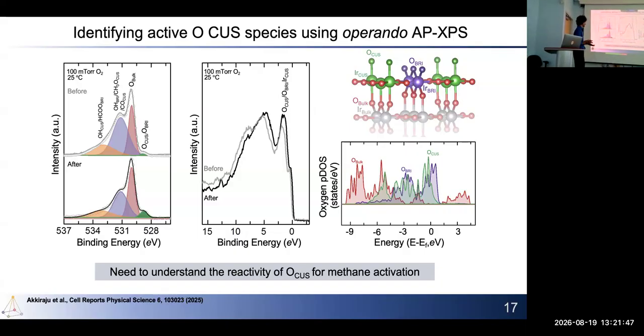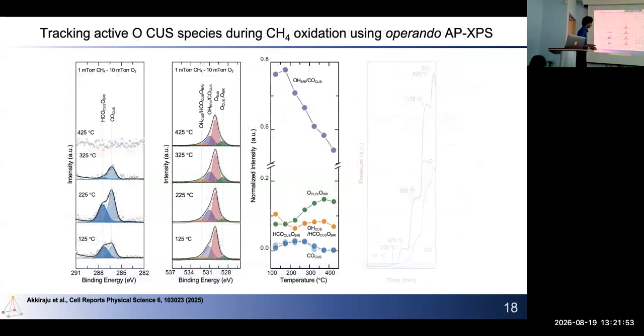Now the question was, does this species actually contribute towards reactivity for methane? In these operando experiments, the cool thing is that you can change temperature and you can also track the products that come off when you run these reactions. So here we ran the reaction from 125 degrees all the way to 425 in a methane environment.